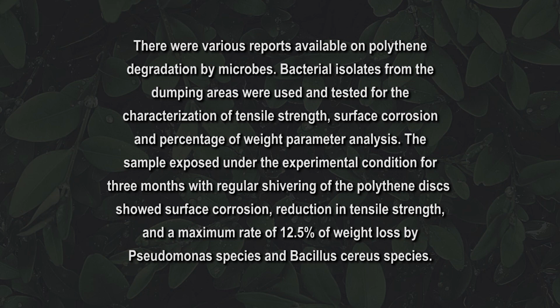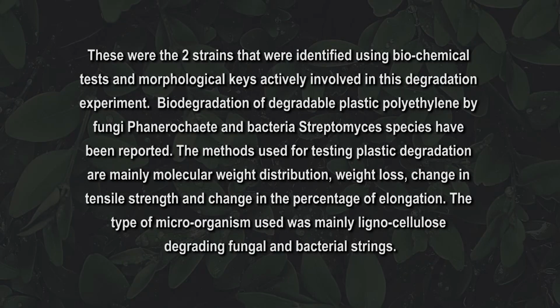The bacterial isolates from the dumping areas were used and tested for the characterization of tensile strength, surface corrosion, and percentage of weight parameter analysis. The sample exposed under the experimental condition for 3 months with regular shaking of the polythene disc showed surface corrosion, reduction in tensile strength, and a maximum rate of 12.5% of weight loss by Pseudomonas species and Bacillus cereus species. These were the 2 strains that were identified using biochemical tests and morphological keys actively involved in this degradation experiment.